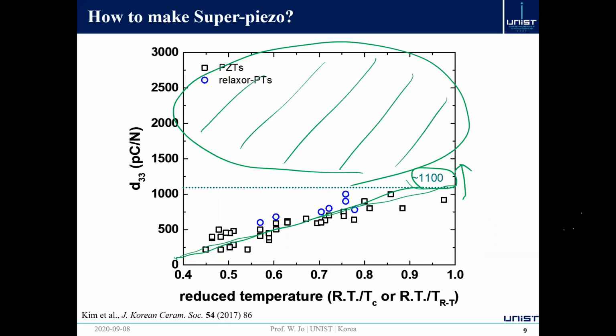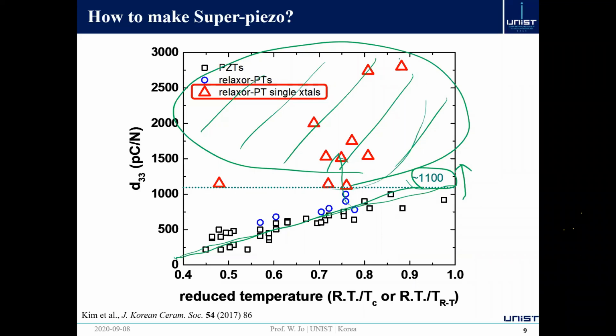I did another survey of the literature, and one of the ways to overcome this limitation would be to work with a single crystal. Even though single crystals don't fit the linear line or any tendency, most relaxor-based single crystals go above this upper limit.